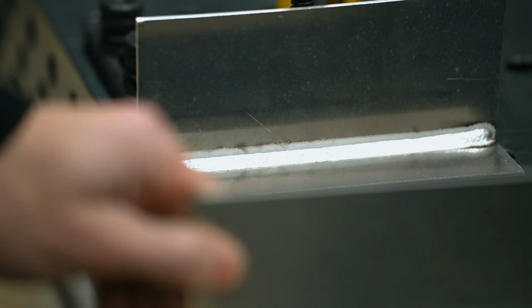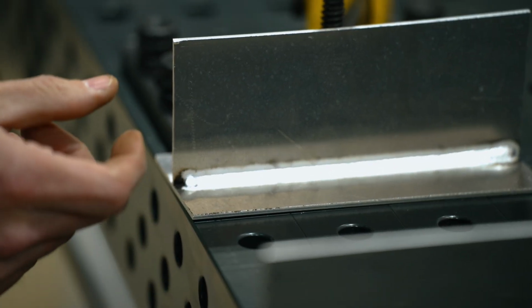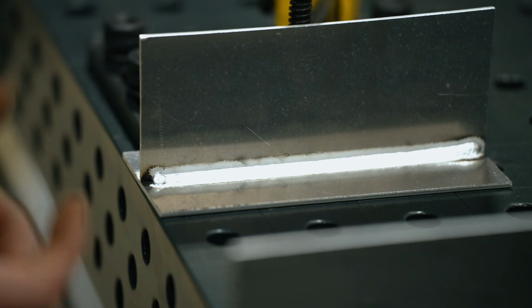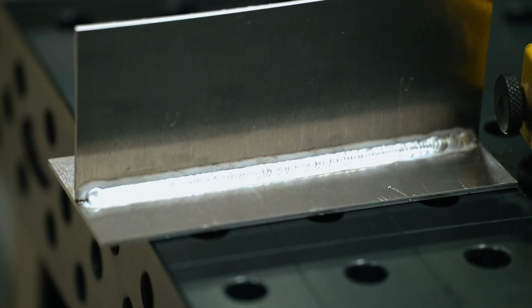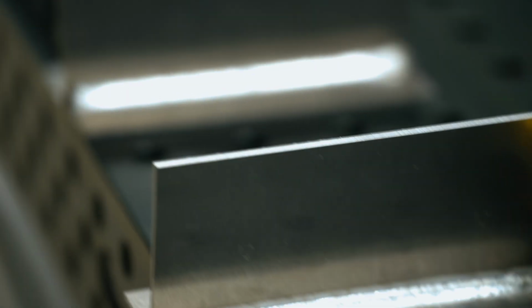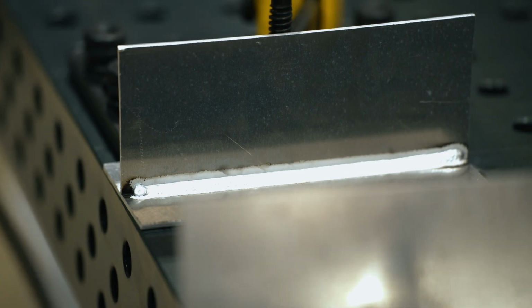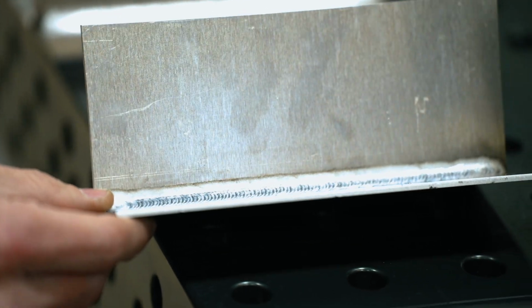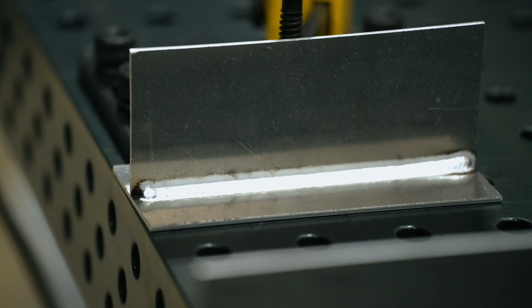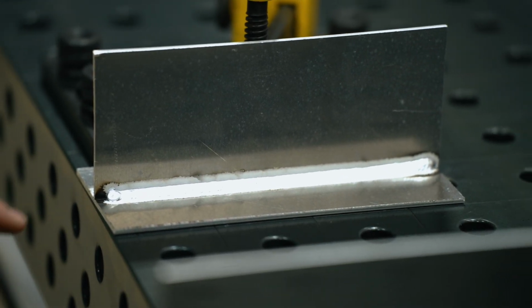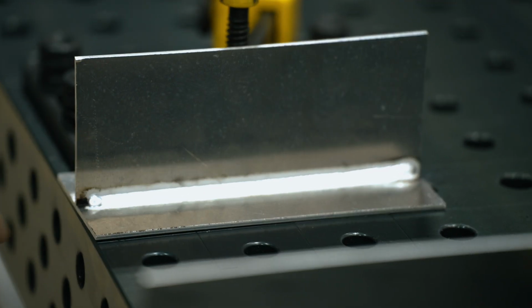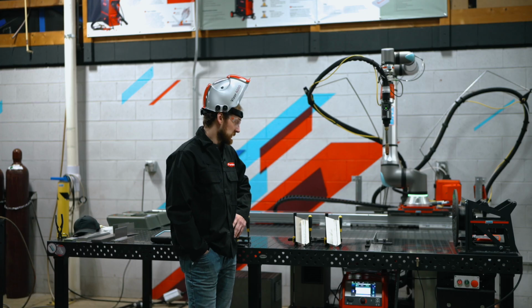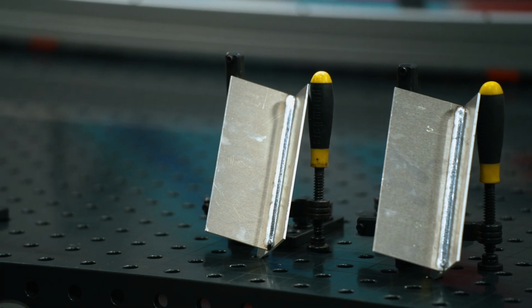So with this, you'll see that your bead is actually narrowed up a little bit more because you're spending less time on the hot side. So your overall heat input is going to be reduced, and your puddle isn't going to be as wide or wet out because your wire feed speed is going to be lower throughout the process, and then your stack of dimes is more apparent.